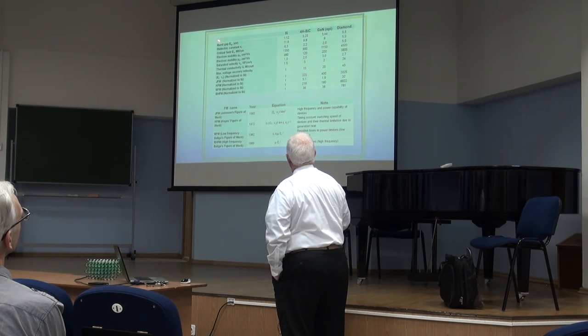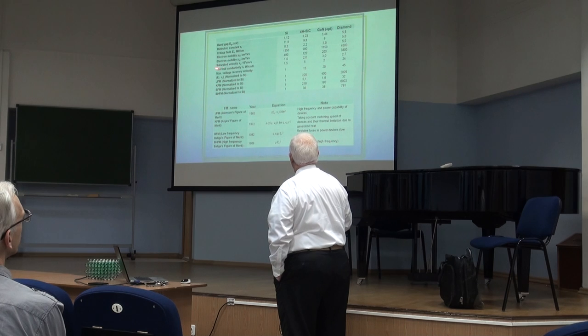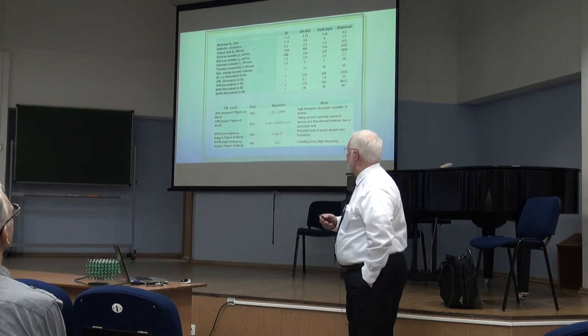diamond. And so here's the band gap, the dielectric constant, critical field, i.e. the insulating strength, the electron mobility, and this is in this film, and the hole mobility, saturated velocity, thermal conductivity, etc. So these are the values for each of these semiconductors in the best scenario.